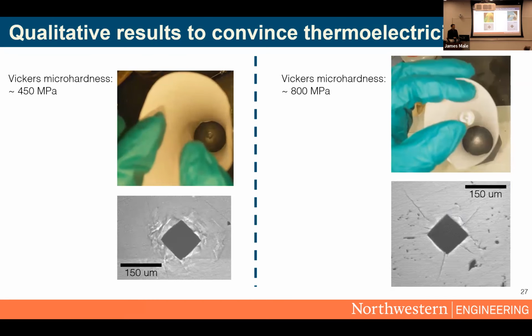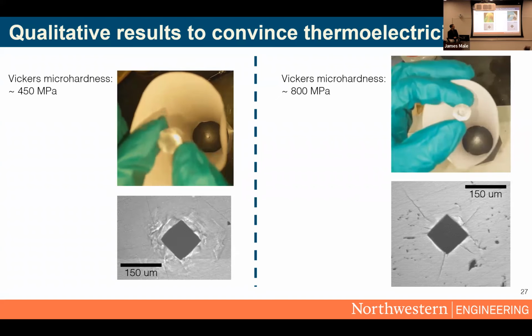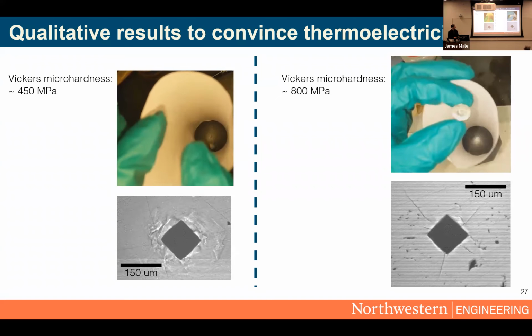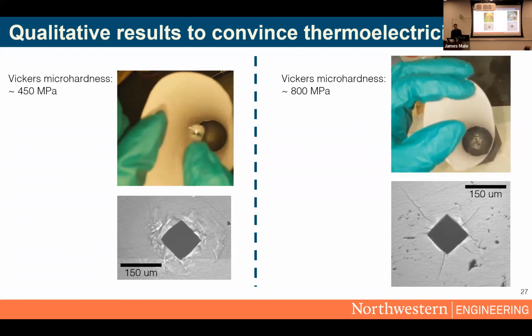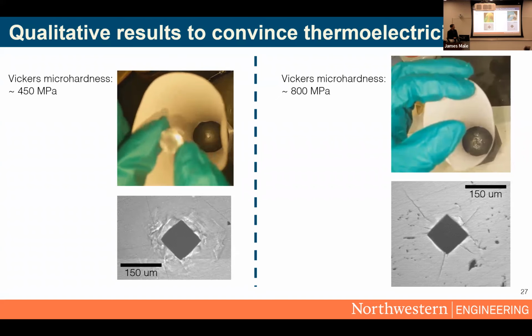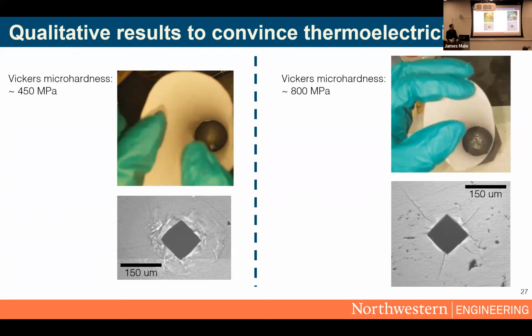And to convince you that high hardness is not necessarily a good thing, I have these very scientific drop tests where I make my material and I drop it down a tube of paper. These ingots that ultimately had a very low hardness don't break easily at all, even if I drop them 10 times. And the Vickers indentation I do shows instances of dislocations and plastic deformation. If I look at one of these high hardness samples, I can drop it from 3 inches and it might shatter. So these things are nowhere near as tough. And my Vickers indentations give me a higher hardness, but they also show all this brittle cracking.